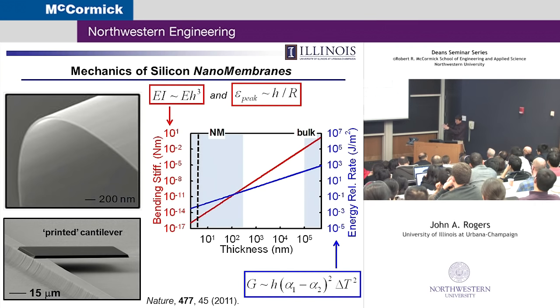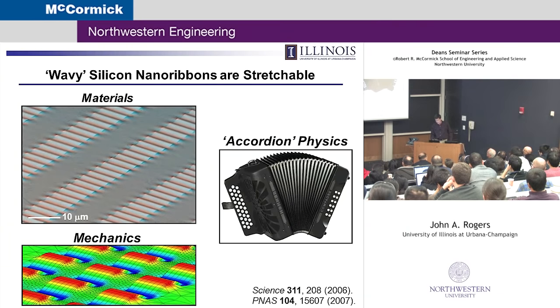So what you need is not only bending, but stretching in the sense of elastic response to large strain deformation. And there's no limit in thickness that will get you into a stretchy form of silicon just by making it thinner. It's much more bendable, but still not stretchy. So how do you do stretching? That turns out to be pretty easy, too.